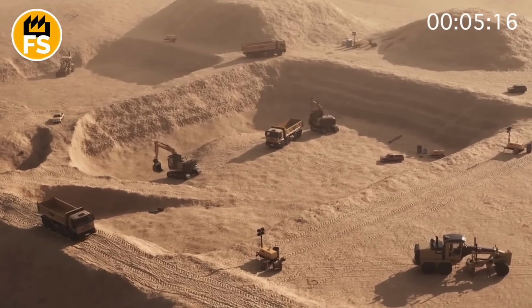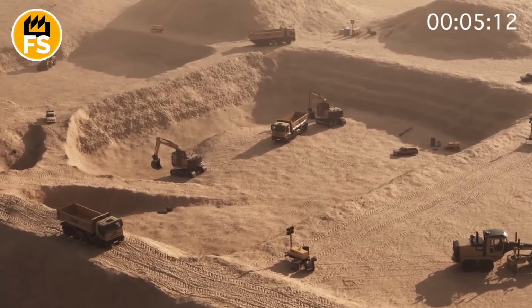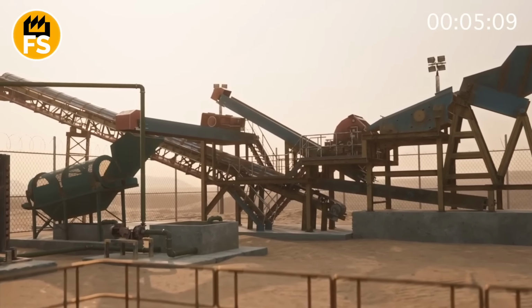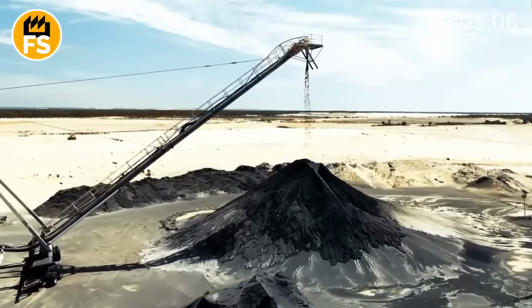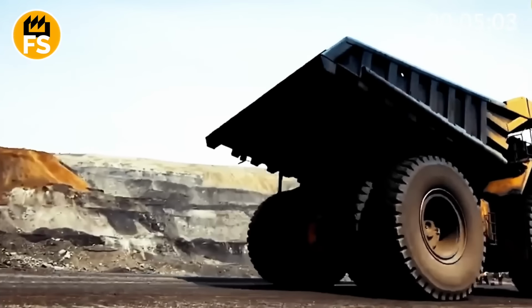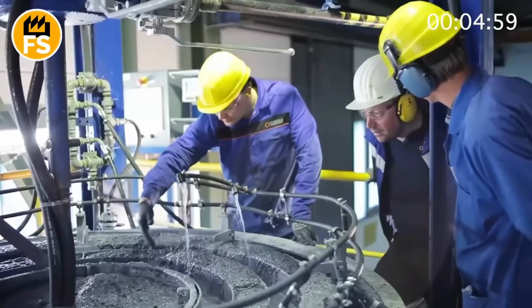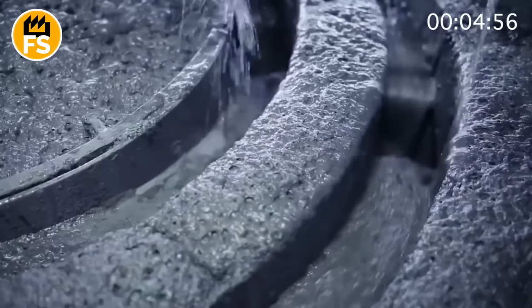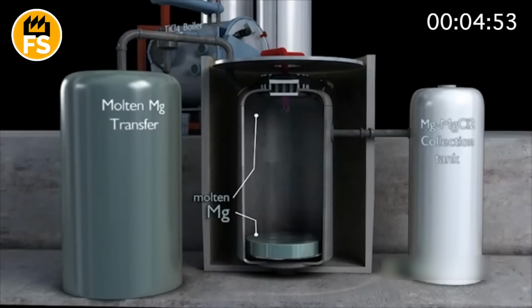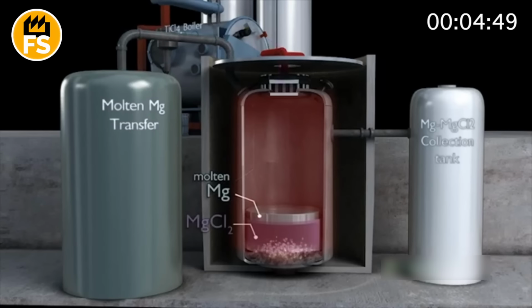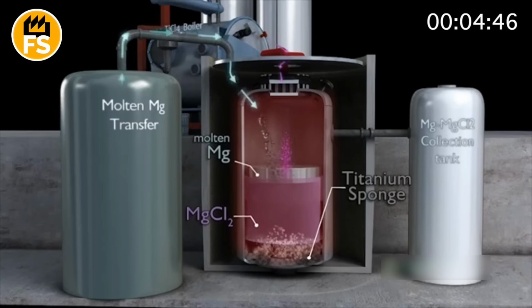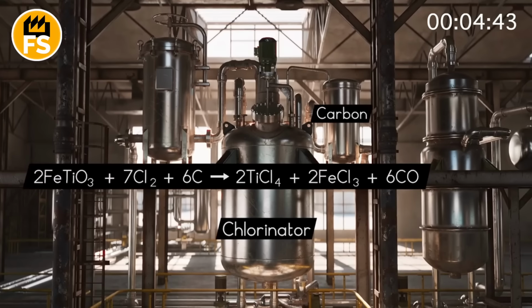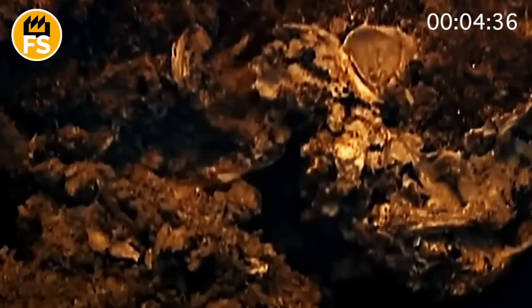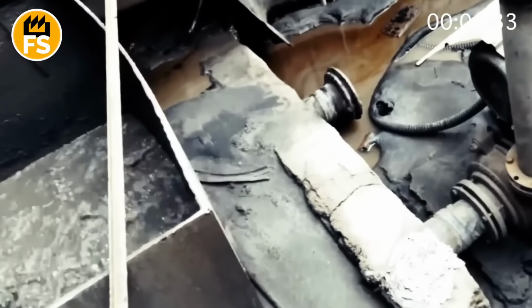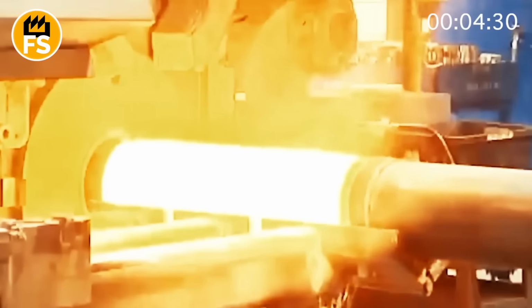The initial stages of titanium production are based on a complex multi-stage technological process that begins with the extraction and preparation of titanium-bearing raw materials, primarily ilmenite and rutile. These minerals contain titanium oxides, which must be converted into chemically pure titanium tetrachloride. For this, concentrates of titanium ores are subjected to chlorination in fluidized bed reactors at a temperature of 1,800 degrees Fahrenheit, where carbon and gaseous chlorine react with the raw material, forming titanium tetrachloride and carbon monoxide. This tetrachloride contains impurities of other metals, which are removed by distillation, obtaining high-purity technical titanium tetrachloride.